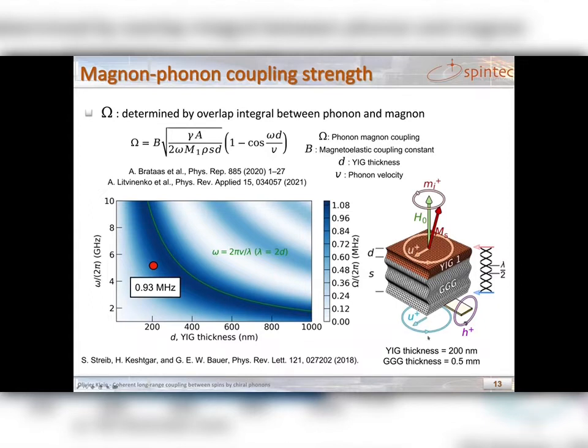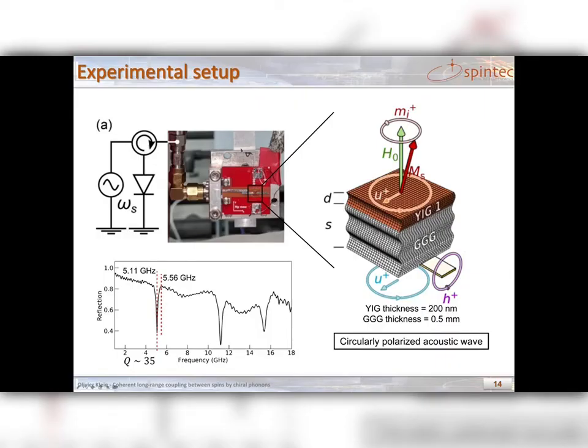So we will give you an example where we use a 200 nanometer thick YIG, and we will be working at 5 gigahertz, and in this case, the coupling strength expected is about 1 megahertz. So we first present our experimental setup. We use a microstrip line cavity with a quality factor of about 35 and a resonance frequency of 5 gigahertz. The sample is placed at the middle of the bow tie, and we measure the reflected microwave power.